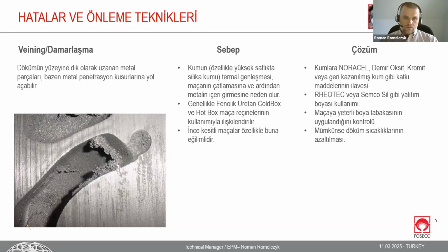What's more, veining itself is the beginning of penetration, and it depends on the situation, how the metallostatic pressure is, and how big the casting is as well. In the first period of time we will have veining, and just after, if it's a bigger casting with longer solidification time, the molten metal is super liquid and is pushed into the core, and we will have metal penetration. As I partly explained, solutions: use different sand, the sand grain distribution, and special coatings to reduce these tensions and expansion in the mold or core.